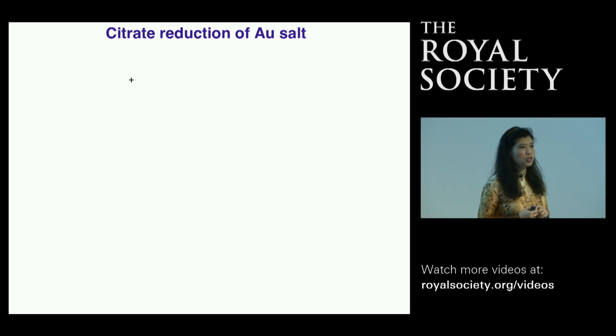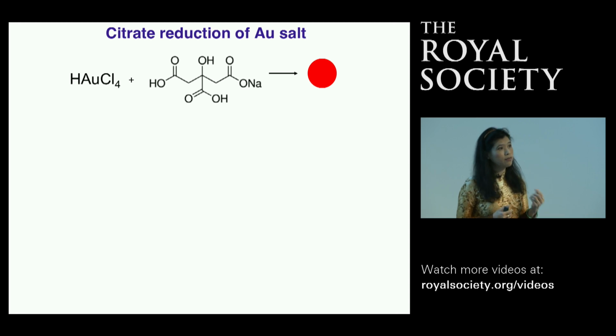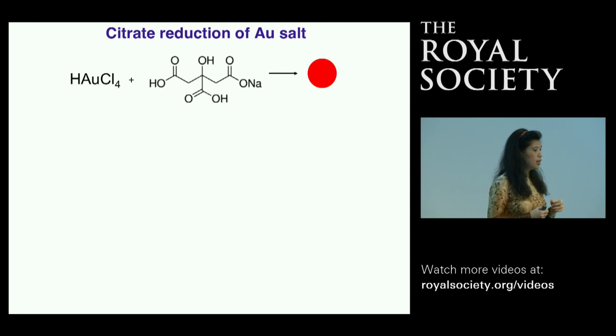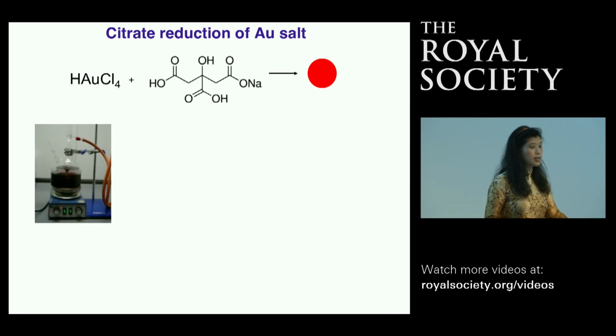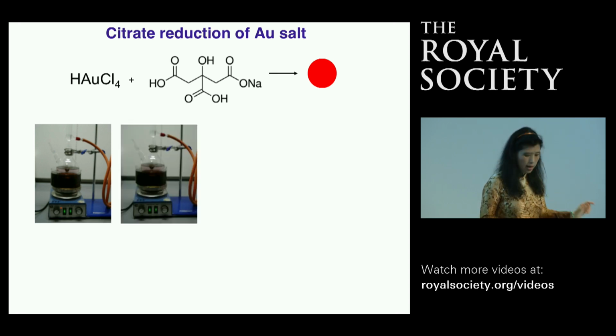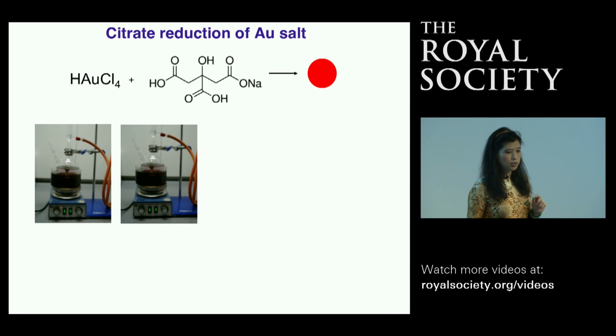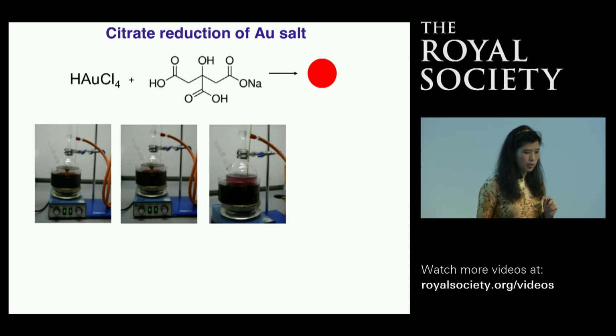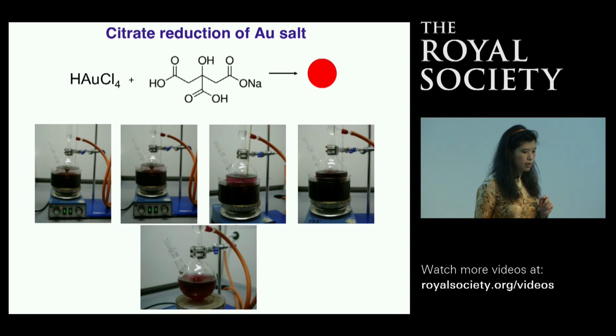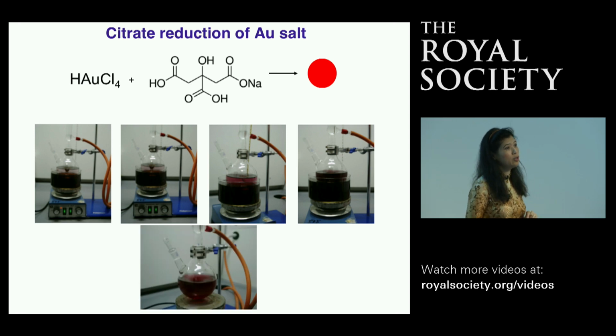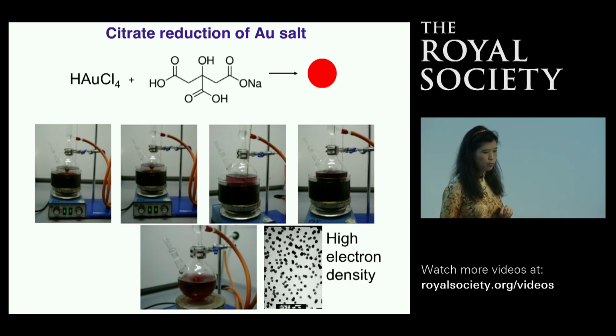So now here, I'm just showing you very quickly how the gold nanoparticles were made using a very simple method, and Turkevich already used this technique using the gold salt and citrate, and again, there's the lemon. You can see that the gold first looks a very pale color, and then with time, it gets darker, and then you get a beautiful ruby fluid of gold nanoparticles.